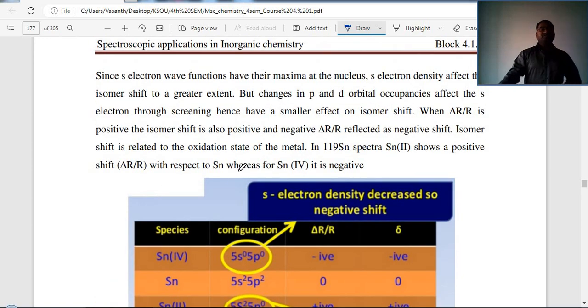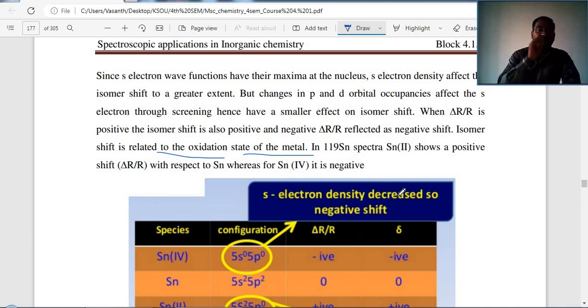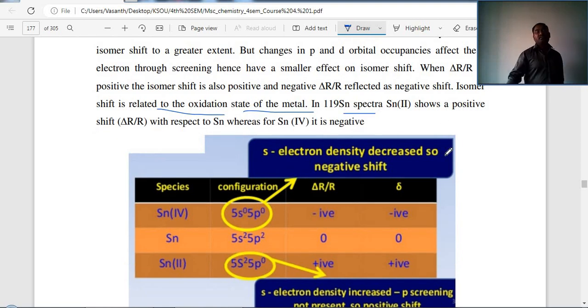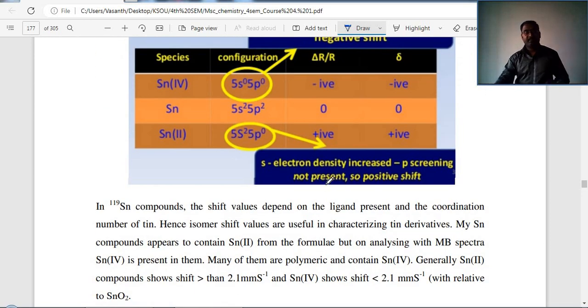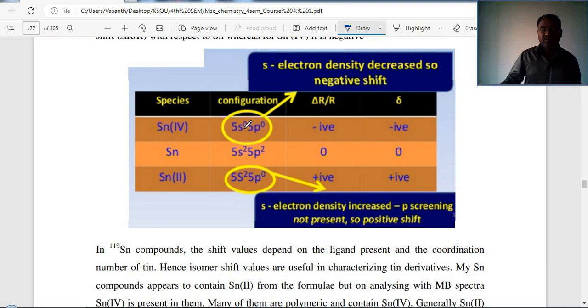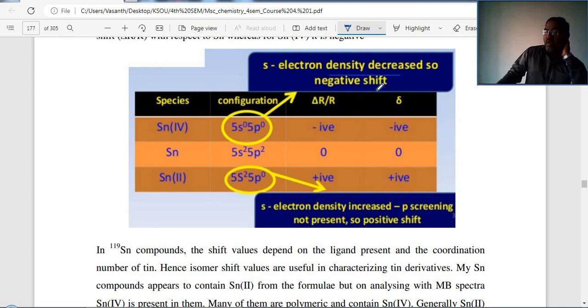Okay, here we observe that the isomer shift is related to the oxidation state of the metal. In tin spectra, Sn2+ shows a positive shift with respect to Sn, whereas Sn4+ is negative. This was Sn4+, 5s0, 5p0, so the electron density decreases, so a negative shift. In Sn2+ the electron density increased, p screening is not present, so a positive shift.